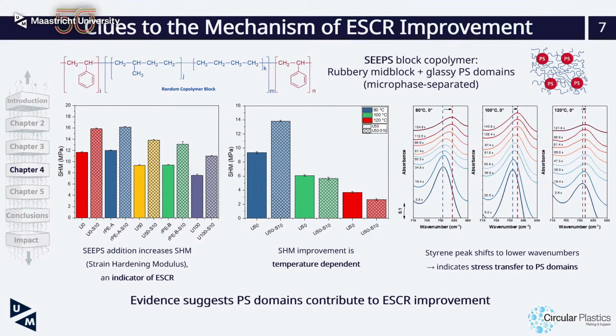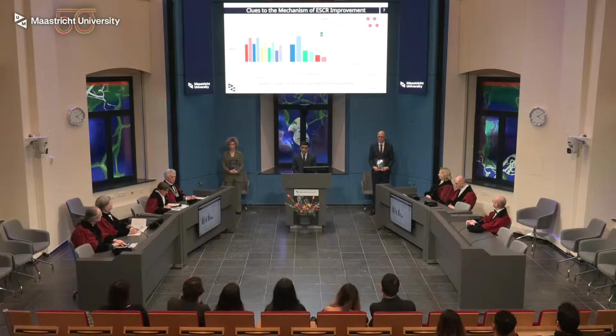However, this improvement disappears as we increase the temperature and reach a temperature that, interestingly, is the glass transition temperature of polystyrene. To investigate this further, we performed FTIR tensile experiments. During that strain hardening region, the styrene peak shifts to lower wave numbers, indicating that polystyrene domains participate in load transfer. Together, these observations suggest that rigid polystyrene nanodomains contribute to improvement in ESCR indirectly.